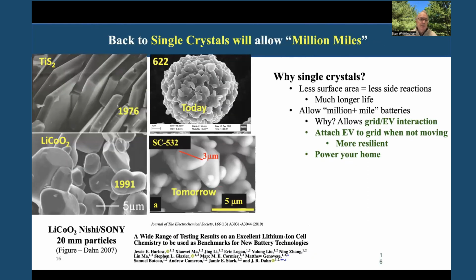I mentioned earlier at Exxon, we started out with these single crystals. So I'll show you on the top left here. These are several millimeters in the plane, so very large. SONY wanted large single crystals of lithium cobalt oxide to make it very safe. The higher the surface area, the more reactive the material is. So you want to reduce the surface area. But to get the power of the batteries up, there's been a tendency of late to go with smaller particles.